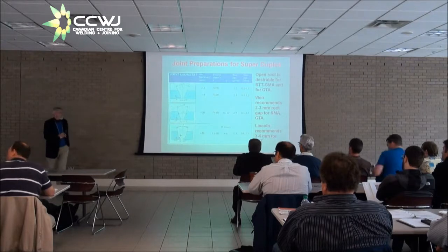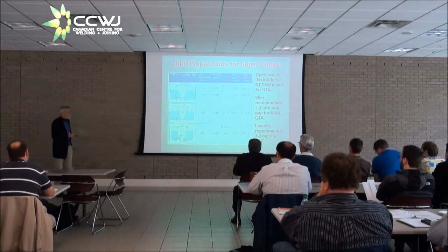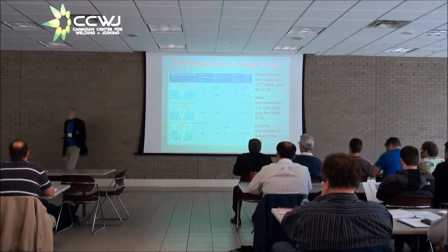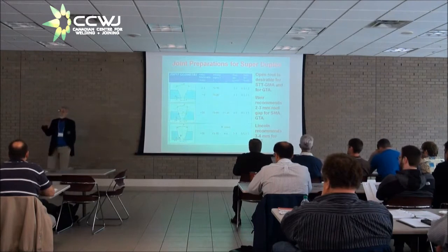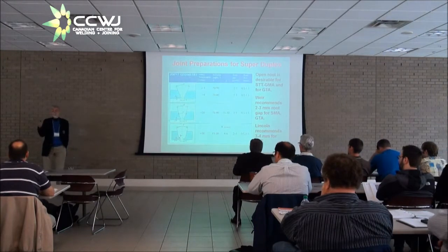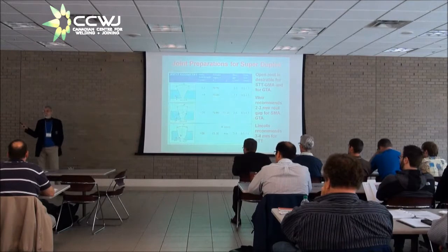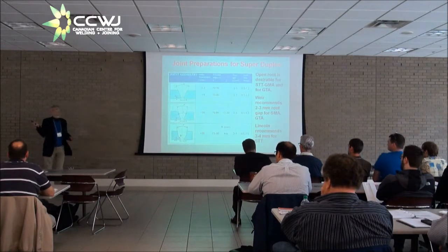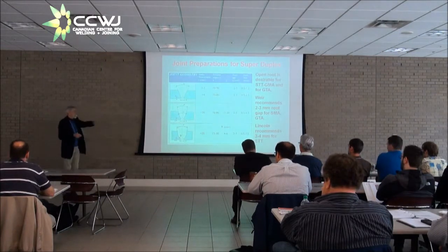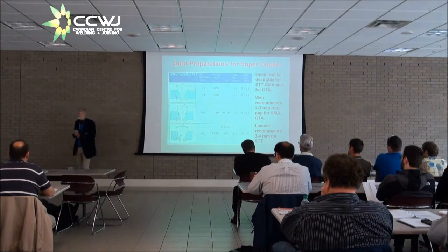Some people say 3 to 4 millimeters, depending upon which welding process you're using. Now this STT, that's surface tension transfer. That's a Lincoln trade name for gas metal arc short circuit transfer with a controlled waveform. And there are other people who make similar equipment. They all come to the 3 to 4 millimeter recommendation for root gap.